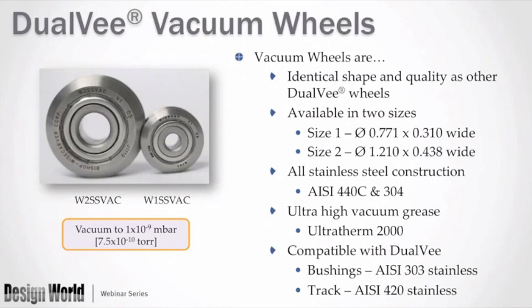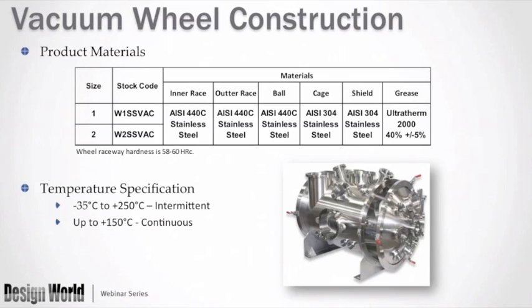So one of the newest products from Bishop-Wisecarver is the vacuum wheel. The vacuum wheels are the identical shape and quality as other dual V guide wheels, available in the smaller sizes, size 1 and size 2. And it's an all stainless design, including the ball cages on the inside, which are 304 stainless. And we use a special ultra-high vacuum grease, which is Ultratherm 2000. And it's capable of reaching vacuums of 10 to the minus 9th millibars, which is considered ultra-high vacuum. And it's also compatible with the standard 303 stainless bushings and 420 stainless track.